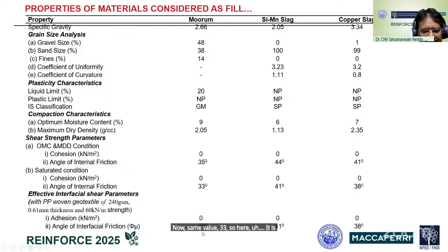It has a maximum density of 2.05 and its shear parameters in OMC, MDD and saturated condition, in a drained direct shear test, are reported. It has an effective angle of internal friction of 33 degrees, and when its interfacial shear parameters were assessed from the pull-out test, it yielded values above the shear parameter obtained in a drained condition on the material itself. In such a case, we need to limit it to the same value, 33. So here it is 33, right? By mistake, it is typed as 35. It is limited to 33.